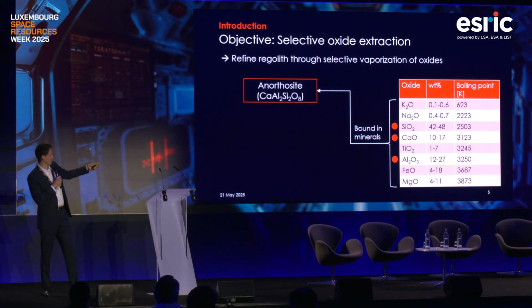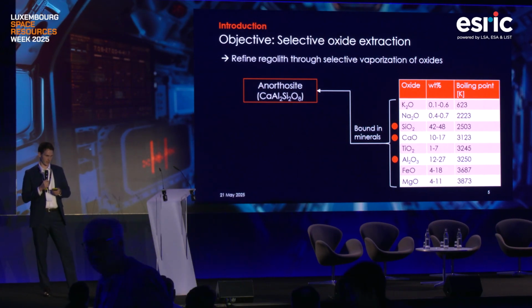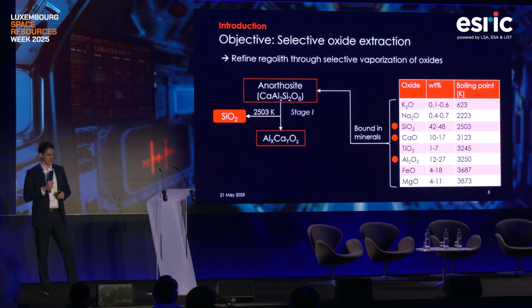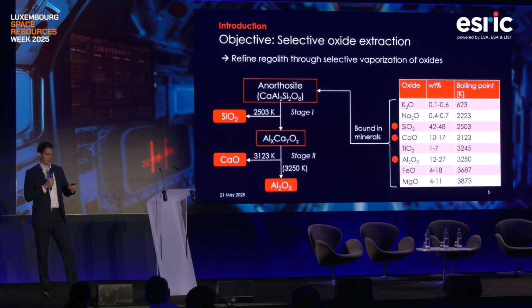We see the boiling points according to the oxides that are present in the regolith at atmospheric pressure. If we simplify this now using only anorthosite, which has silicon dioxide, calcium oxide, and alumina, or anorthite, we would take a first stage to boil out the first oxide according to this table, silicon dioxide, which leaves us with a residue containing only aluminum, calcium, and oxygen, and perform a second stage to boil out the next oxide, leaving us with 3 refined materials, ideally.